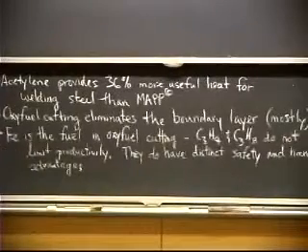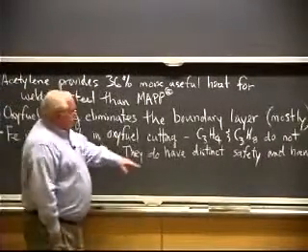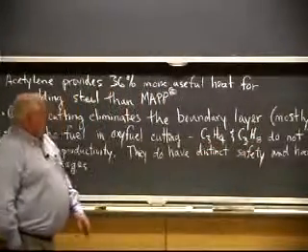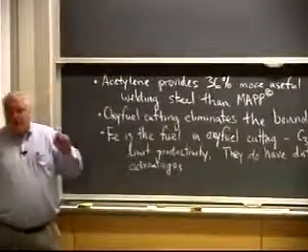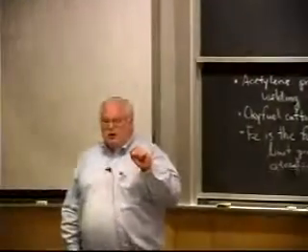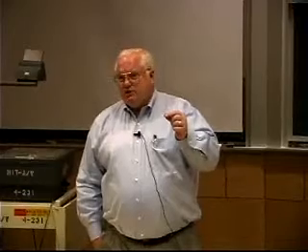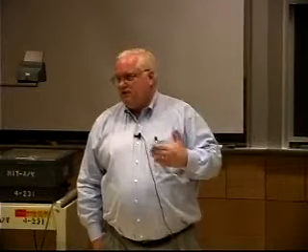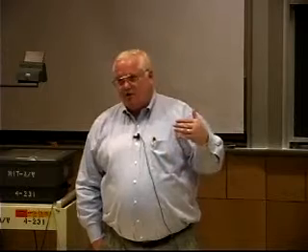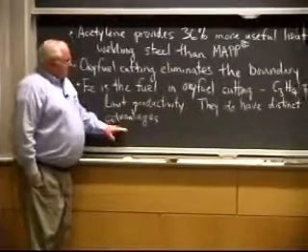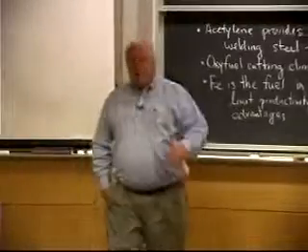Iron is the fuel in oxy-fuel cutting. It really doesn't matter whether you use MAP gas or propane or gasoline. People actually use gasoline sometimes for oxy-fuel cutting. It's not going to limit the productivity, because the time it takes to initiate the cutting process, where you're using the oxy-fuel flame to start the cut, typically takes 10 or 15 seconds. And if the whole cut's taking several minutes, it really doesn't matter if it takes 10 seconds or 12 seconds. Two seconds out of several minutes of cutting time is really not going to make a significant difference in productivity. There are distinct safety advantages and handling advantages when you go to something other than acetylene.